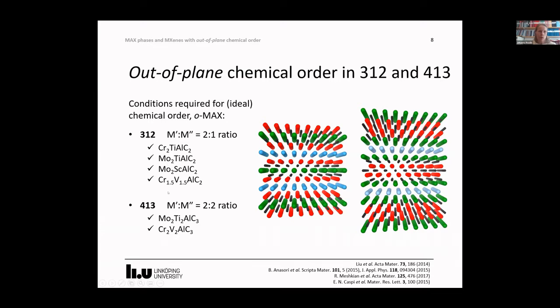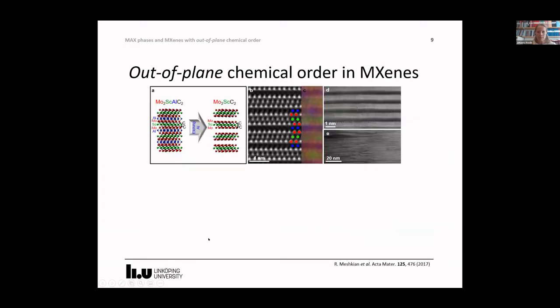The first o-MAX phase was chromium-2 titanium aluminum carbide, discovered by Liu and co-workers with out-of-plane ordering of the M elements. This was followed by more phases and also by corresponding 413 phases. The o-MAX phases are of course interesting by themselves, but as important is the fact that they can be converted into corresponding MXenes with out-of-plane chemical ordering. The first example I show is the 312 o-MAX, moly-2 scandium aluminum carbide. And you see this chemical ordering evident from the atomically resolved EDX here. And this is what the MXene looks like.